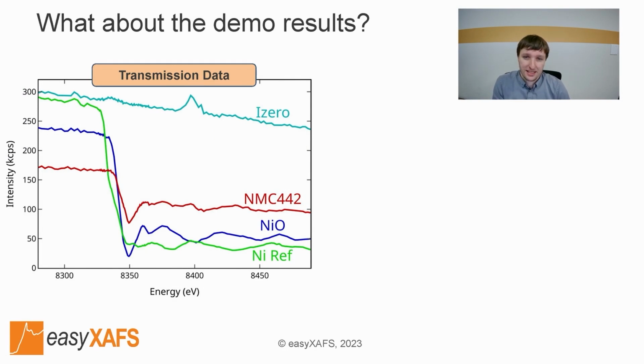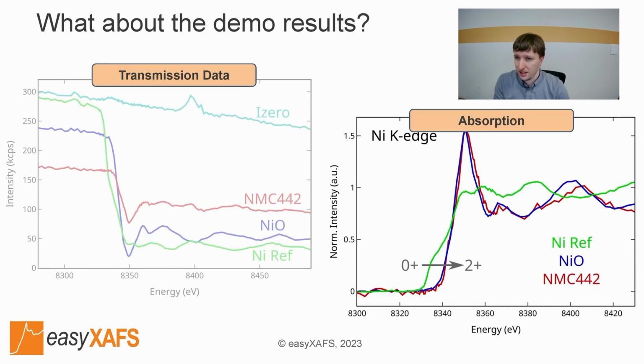With limited processing, we can convert the transmission results into corresponding absorption spectra. In the absorption spectra, there's a clear shift between the nickel reference 0 and the 2+ nickel oxide and NMC442 samples. In addition, there are slight differences between the NMC442 and nickel oxide materials associated with differences in structure. This short measurement highlights the capabilities of XANES to give us direct insight into the oxidation state, even within a few minutes of measurement.